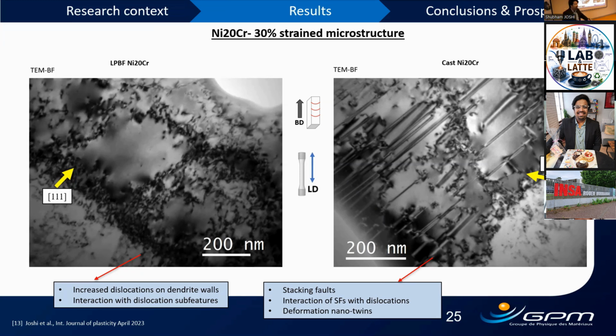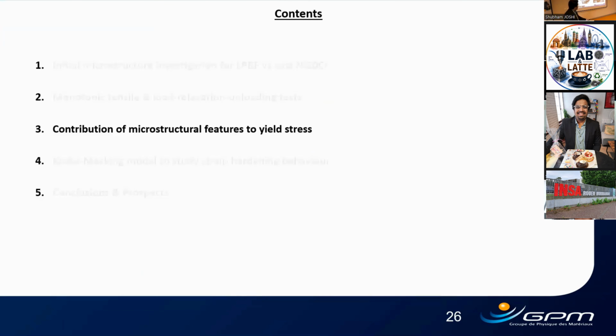So there is clearly even a post-deformation microstructure difference as well. So as of now, coming back to the question, we can understand that yes, there is a difference in initial microstructure, there is a difference in mechanical properties, and there is clearly a difference in post-deformation microstructure. We could also narrow it down that somehow back stress, dendrites, and grain boundaries are responsible. But again, the question that we asked is how much, and which exact parameter is missing.